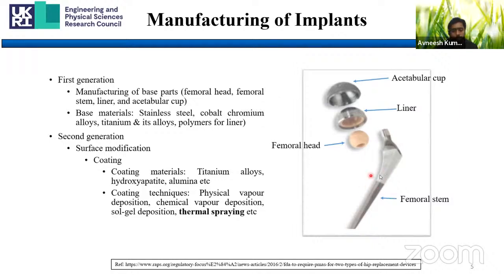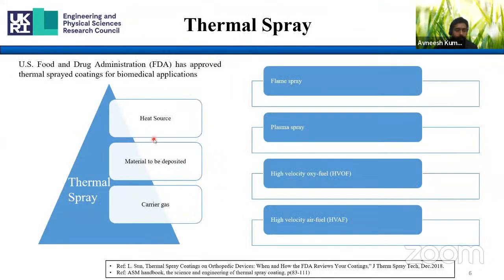Or in some cases, they have tried to improve the surface roughness in order to get better biological properties. For that, they have used grit blasting. And also people have used coatings to get better biological, mechanical or chemical properties. For coatings, people have tried different materials, including titanium based alloys, hydroxyapatite, alumina, zirconia, and many more. And the technologies they have explored include physical vapor deposition, chemical vapor deposition, sol-gel deposition, and thermal spraying also. Thermal spray is also accepted as a biomedical coating technique by the US Food and Drug Administration.